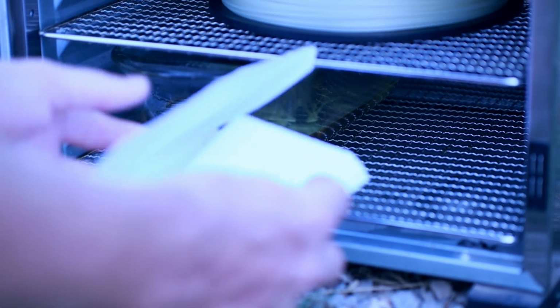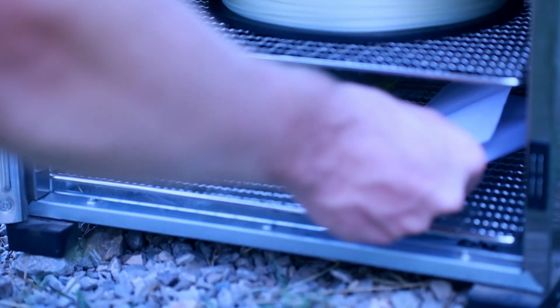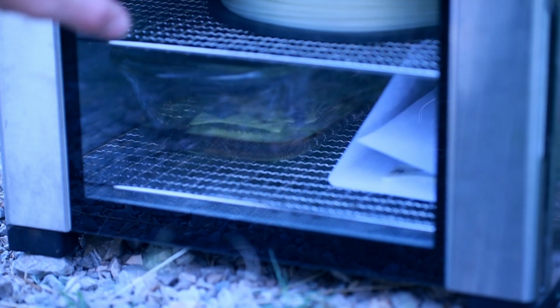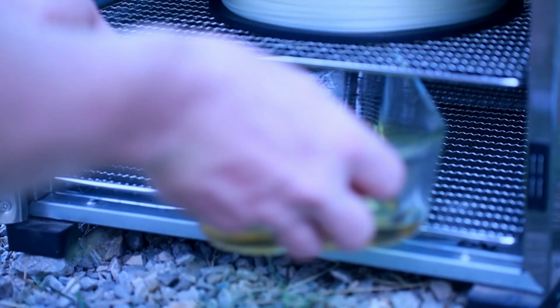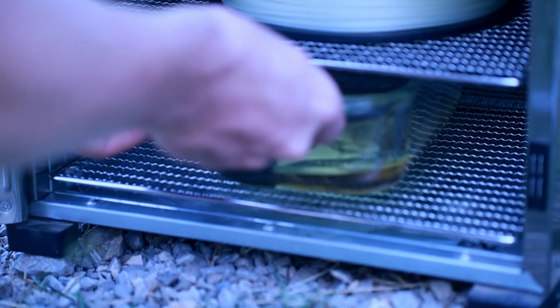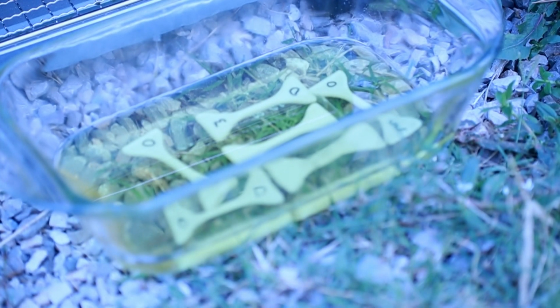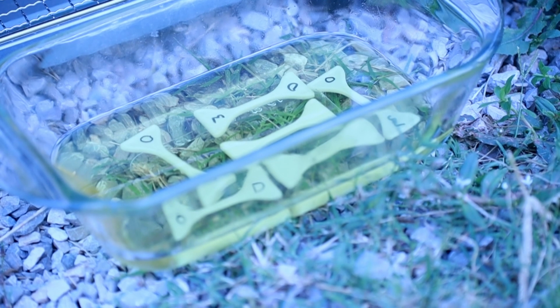The second set, I annealed at 185 degrees Fahrenheit for 2 hours in hot air, basically in my filament dryer. Then I allowed it to cool down to room temperature and popped it right back into my dry box. The next set of samples I processed a little bit differently. I placed them into an oil bath and annealed them for 2 hours, just like the other samples, but this time in the oil bath. I then let them cool down to room temperature gradually, and I allowed them to sit in the oil bath for an additional 24 hours to absorb oil.